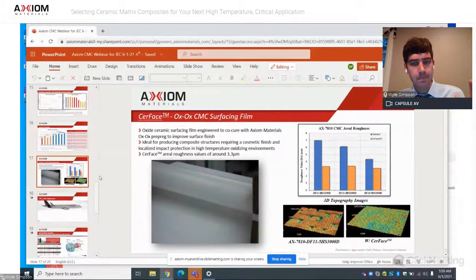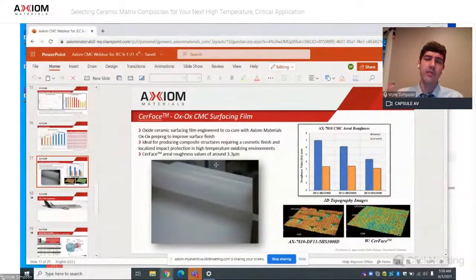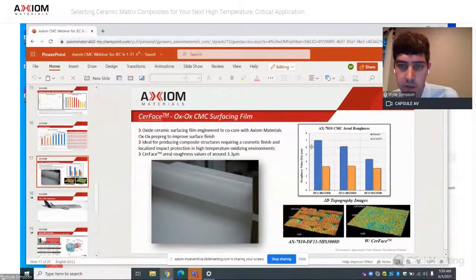Another product that we have to offer that's pretty unique is a CMC surfacing film called CerFace, and this is meant to co-cure to the surface of these ceramics to reduce surface roughness as well as reduce surface porosity and create a more cosmetic finish. You can see here the difference between the surface roughness of prepreg with it and prepreg without it, and the stark difference you're seeing between those two systems.